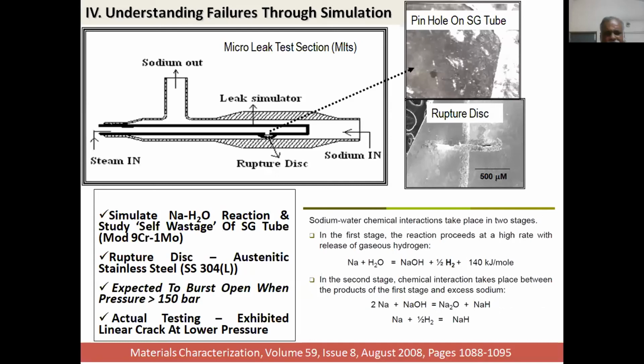Our mechanical engineers wanted to understand this failure. They allowed the steam to pass through a tube, a steam generator tube, and they provided a small hole in the steam generator tube, and they closed that hole with a stainless steel rupture disc. Rupture disc means its thickness is very small, about 50 microns or so, and they scribed on the outer side a plus mark as shown here on the right side.